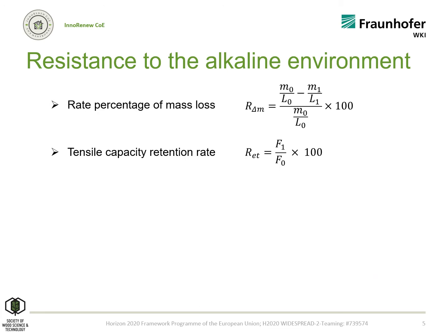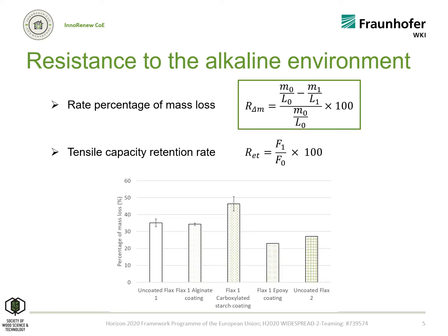We measured the rate percentage of mass loss, which we want as low as possible, and we can notice two things. First, when uncoated, the flax 2 has a lower rate percentage of mass loss than the flax 1. So not all the textiles made of flax fibers are similar regarding the alkaline resistance.